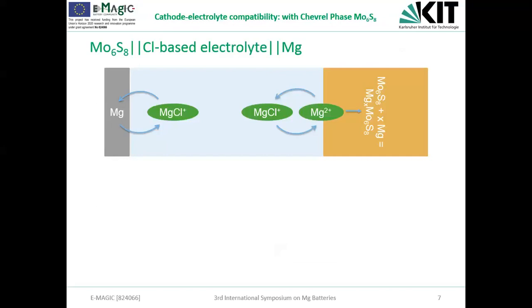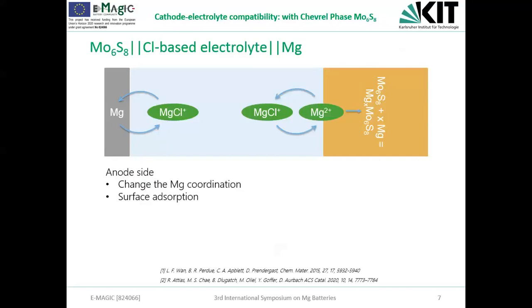as reported previously, the chlorine ion has, let's say, a decisive role in the charge transfer at the interface of both the anode side and also the cathode side. So we know that the chlorine ion has a strong affinity to magnesium, and this will, of course, change the coordination environment of magnesium in solution. Also, that tends to form the adsorption layer, as Doron mentioned before. So this is kind of protecting the magnesium, so that we could, on the one hand, have efficient plating and stripping, and also ensure a prolonged cycle life.